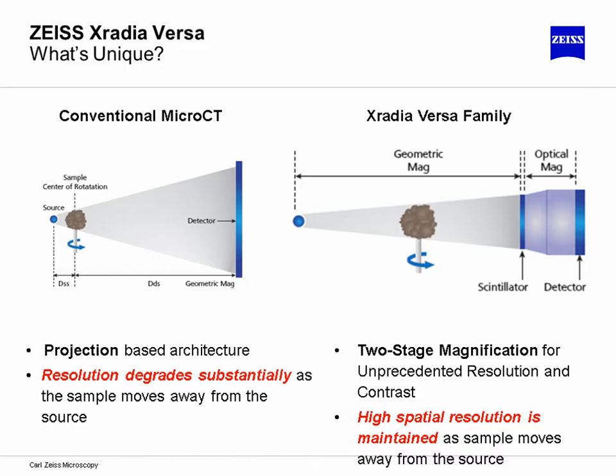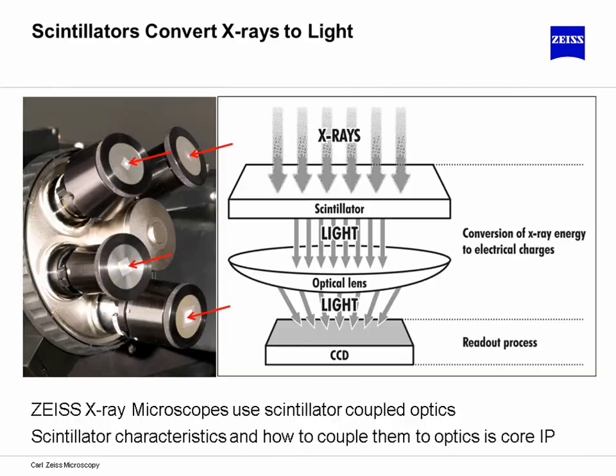Now, the sample dimension and size, or the environment that it's placed in, when you place it in a dual-stage magnification system, allows you great freedom in the ability to obtain high-resolution information at multiple points within the sample. So it's critical to remember that high spatial resolution is maintained as that sample is moved away from the source. Now, this could be a large, awkward-shaped sample or a flat sample that you can't afford to break up. Perhaps you have further experiments or conditions you'd like to subject that sample to, or it's a sample that you've placed inside of a chamber to look at corrosion or look at tensile failure or electrochemical stimulation and cycling. Could be a variety of things. It's really the most flexible platform for obtaining true submicron resolution across a wide spectrum of sample shapes and sizes.